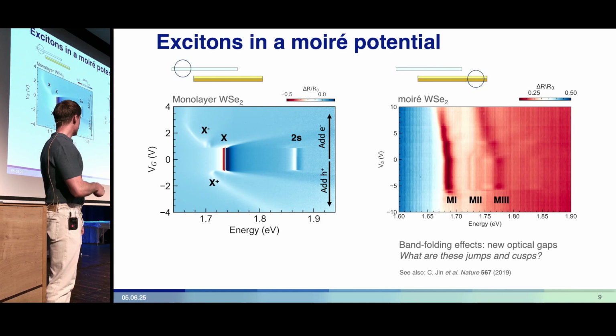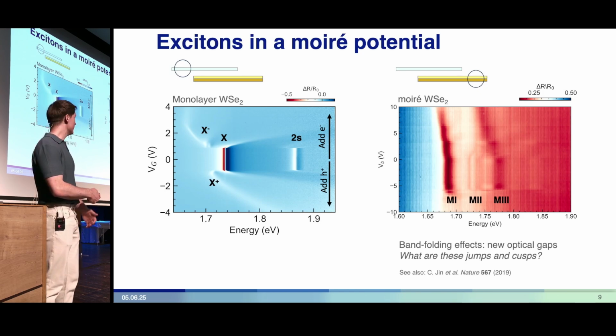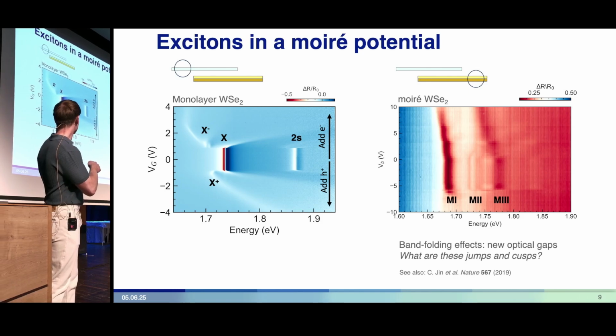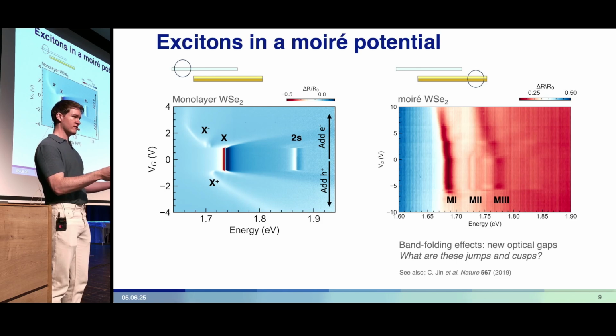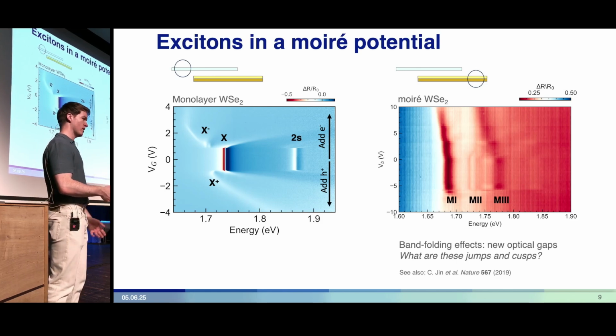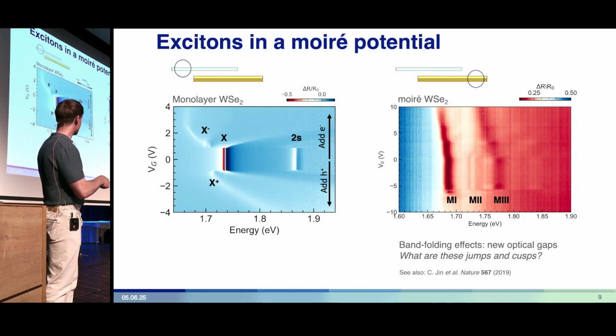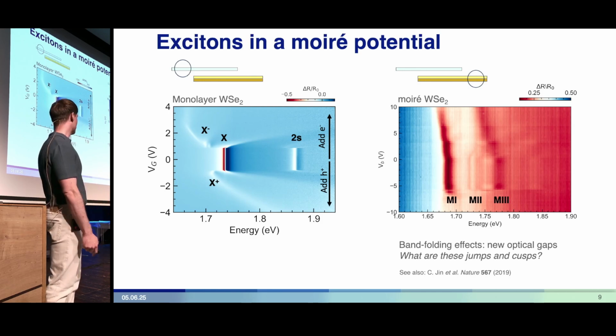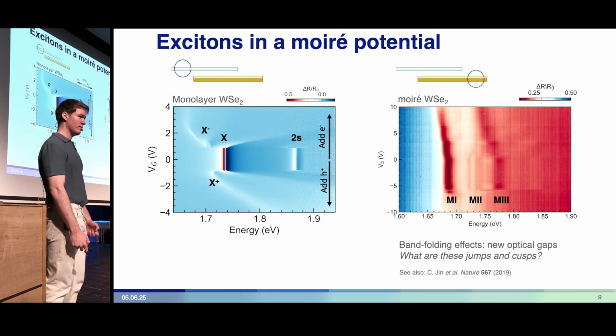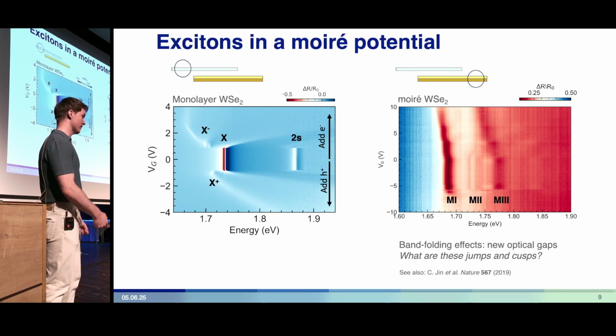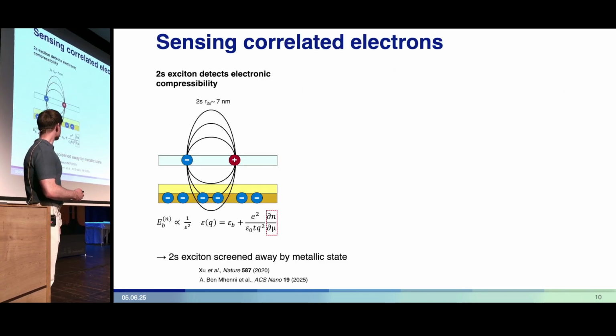So we have these 3 Moiré excitons, M1, M2, and M3, and their evolution with charge doping is rather different from the evolution of the excitons in the free monolayer. Here, the excitons move from one species to the next but evolve continuously, shifting in energy continuously and changing their oscillator strength continuously. Whereas here we have this rather discrete behavior, discrete steps and cusps that happen at particular voltages. I will convince you in a bit that these cusps correspond to band filling in the Moiré layer.